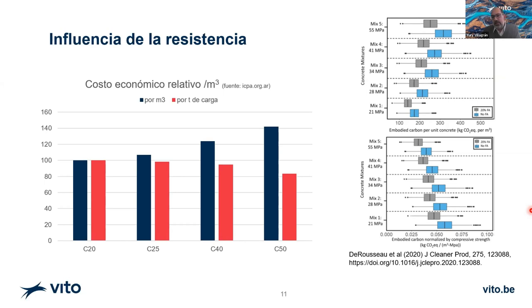This concept can also be explained by the additives. Here we, for example, see a study where the amount of carbon embedded affects the strength as opposed to ordinary concrete and fly ash. But when we normalize by strength, we see that the higher strength levels will have a lower environmental impact.